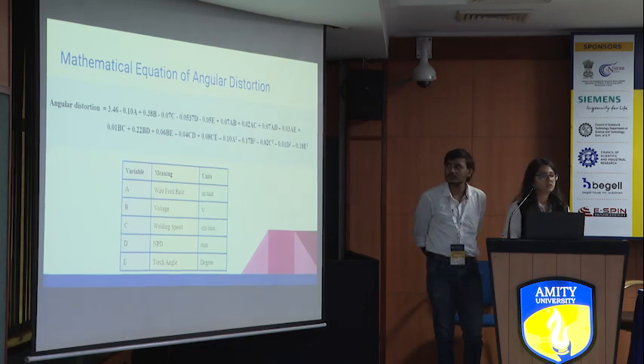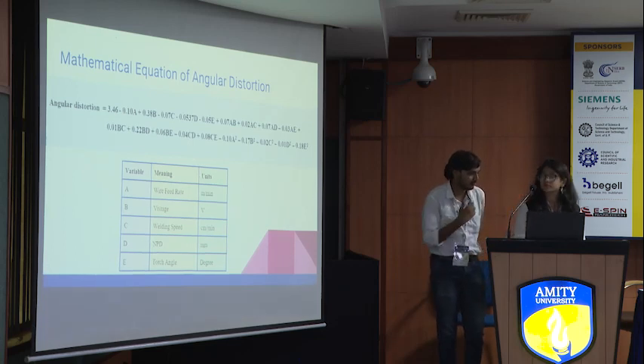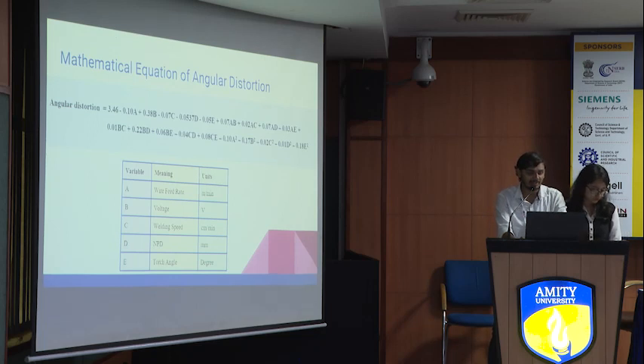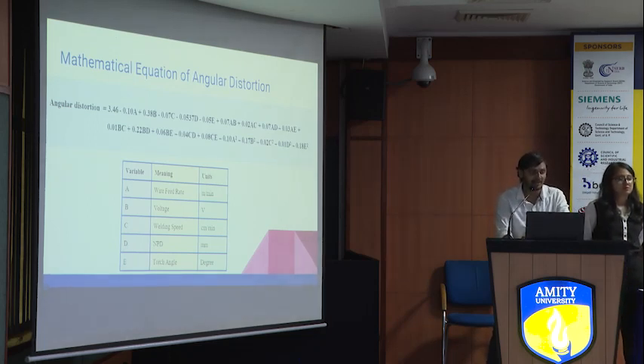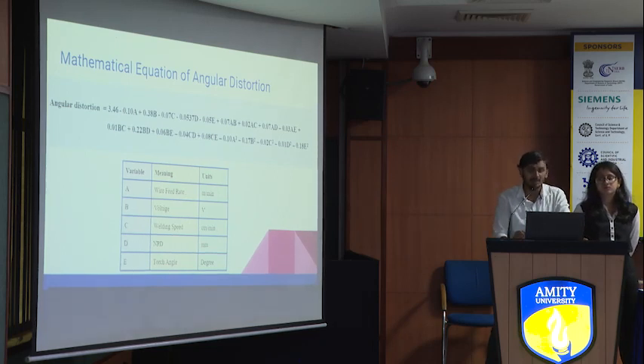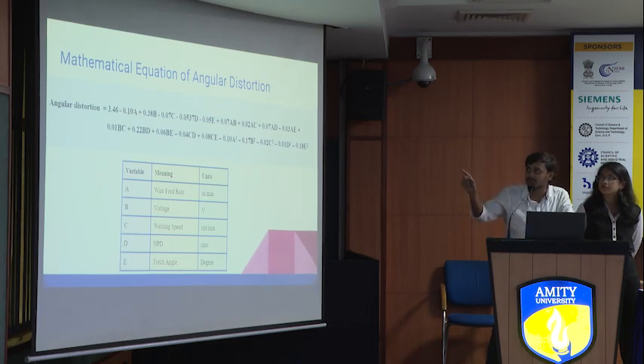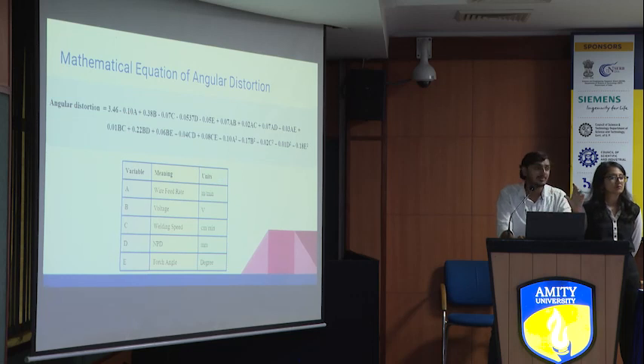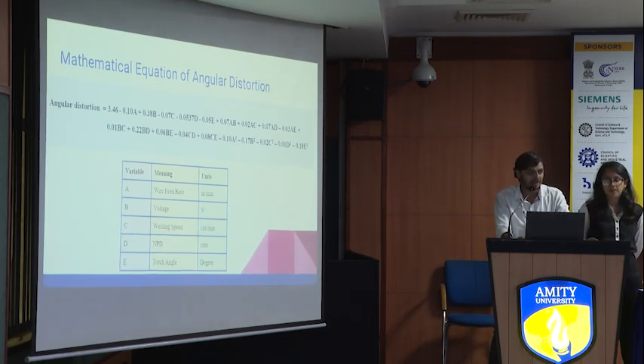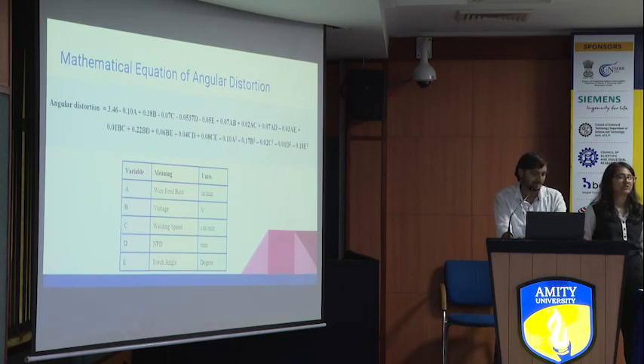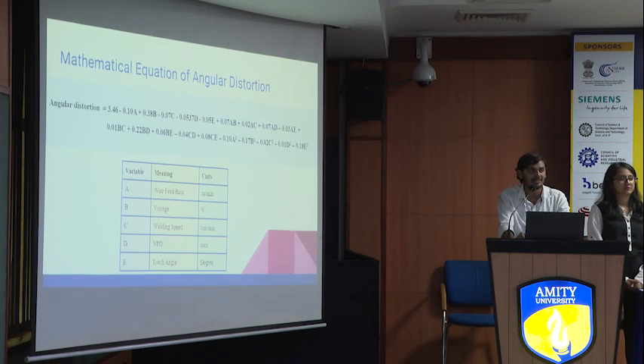So you know the significance of A square and C and all these things? So, sir, in this mathematical equation, you can see that our input parameters are the variables here. A, B, C, D, E represent our wire feed rate, voltage, welding speed, NPD, and torch angle. So, in this equation, let's suppose that the B square value shows a significant increase in the angular distortion. That means that voltage is a major factor basically dominating the angular distortion. So there is a direct connection between voltage and angular distortion. By analyzing this mathematical equation, we came to our conclusions and those graphs.